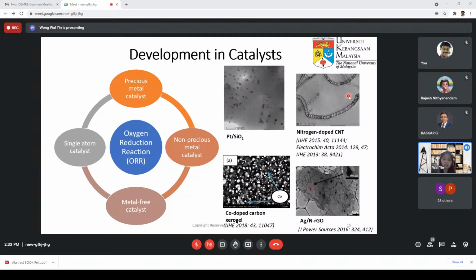Okay, so that triggers the researchers to look for alternative materials. Since platinum itself gives a high overall potential, why not search for other alternative materials as well? So the development comes into different areas. First is the precious metal catalyst, as mentioned, the platinum and also palladium. In this regard, trying to reduce the loading is one approach, and trying to improve the lifespan of the catalyst is another approach that's being progressed. Secondly, the non-precious metal catalyst, this is the main key focus that most researchers are studying, mainly searching for non-platinum catalysts.